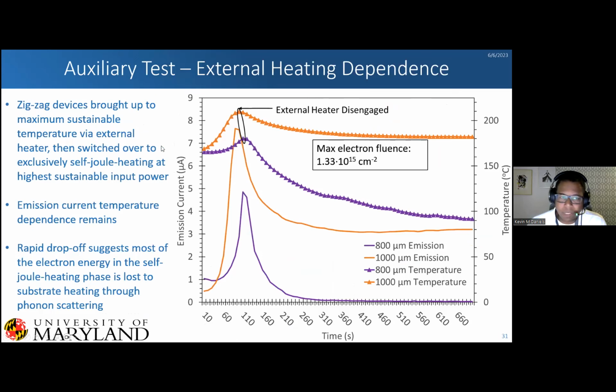And then this was a really interesting test. So what Daniel did was he had one of his zigzag tests. He brought it up to the maximum sustained temperature via the external heater. So here's our temperature here. You can see it go to 150, and you see the emission current go up. And then he switched off the external heater, still applying his input voltage, and immediately self-Joule heating took over, and he saw a drop in his emission current as a result.